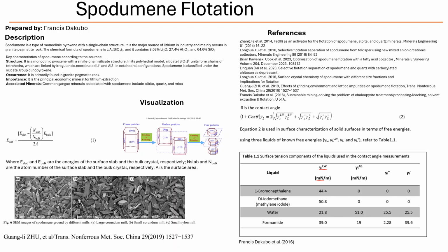That's often the core challenge. Maximizing recovery versus maximizing grade. Push too hard for recovery, and you might pull up more gangue, lowering the grade. Be too selective for high grade, and you might leave some valuable spodumene behind, lowering recovery. Finding the economic and operational sweet spot is key.